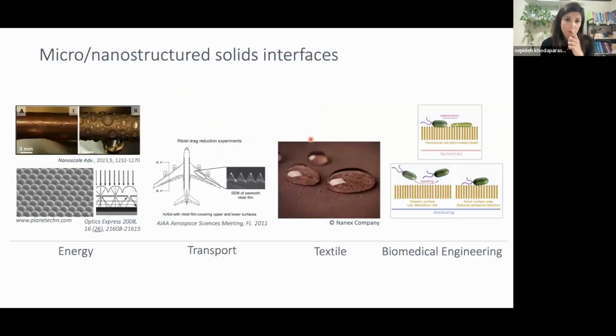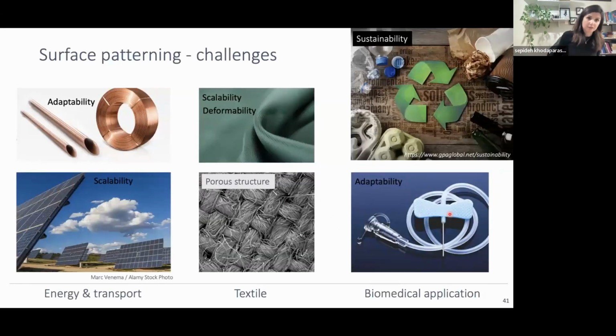But we know that adding surface texture increases energy efficiency of these materials, it reduces drag in many cases, and it reduces the fouling on these surfaces. But one of the issues with creating surface roughness, or at least nano and microscale surface structure, is that most of these materials that you want to create these structures on are already established in different applications. So for example, in energy, most of the materials that you're dealing with are in the form of tubes that have curved interfaces, internal and external. You're dealing with meters of material. So if you want surface structuring, it needs to be a technique that is scalable.